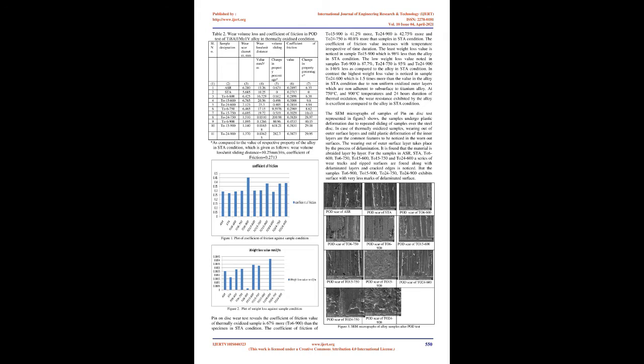2. Experimental details. Titanium alloy received in the form of a rectangular bar of 45 mm, 50 mm, 500 mm is cut into pieces of required dimension. The cut pieces of alloy are cleaned thoroughly using a cleaning agent and applied 2 layers of protective coating before loading to the furnace for solutionizing heat treatment.